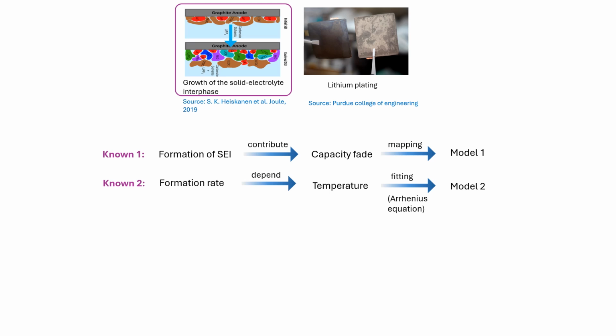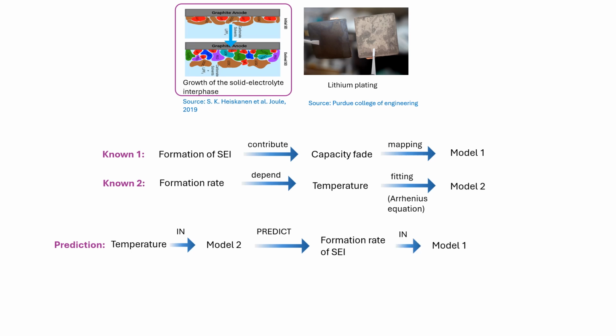Battery cycle life can then be predicted with these 2 models, with temperature measurement being the only input to the model. Here is the workflow. Temperature is input into Model 2, which will predict and output the formation rate of SEI. Then plug in this formation rate to Model 1, and the capacity fading curve of the battery can be predicted. Notice we defined that the battery cycle life ends when the capacity is reduced to 80% of its rated value. So the final predicted cycle life can be found on this capacity fading curve.